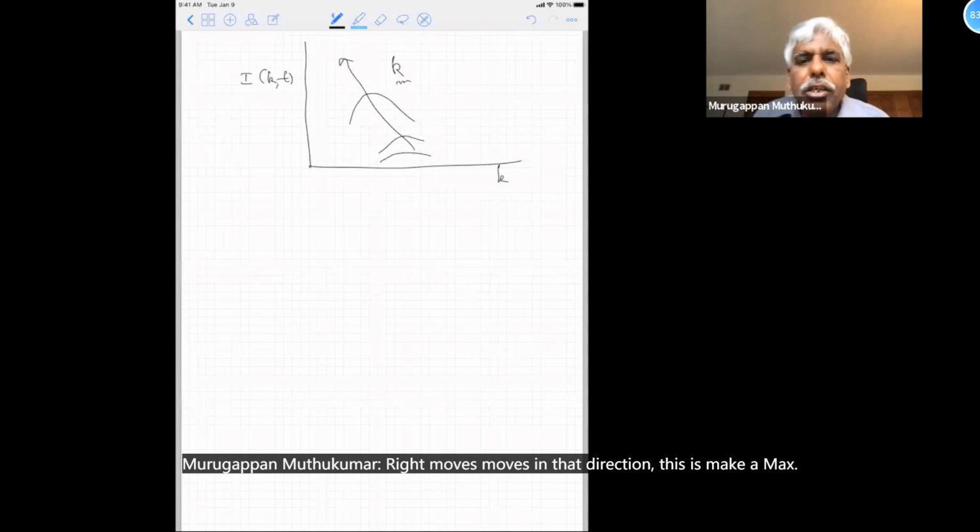Based upon this data, they have plotted the K max. In their paper they use Q, I use K for the scattering wave vector. Q max as a function of reduced time, in a log-log plot, as you see. Here is the early regime, then there's the intermediate regime, and that's the late regime.